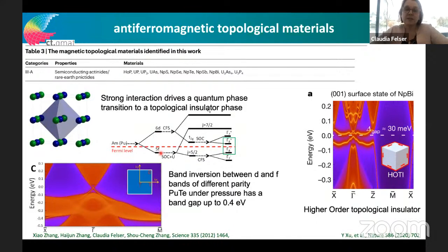This is very interesting because these are all materials in this group of materials which you can see here, which have f electrons, so they are strongly correlated, and they are one of the few already verified or investigated materials where the topology is driven by a strong correlation. So this is, I think, the direction we go nowadays. We look for many, many more of this kind of materials. And here you see the scheme of the band inversion.